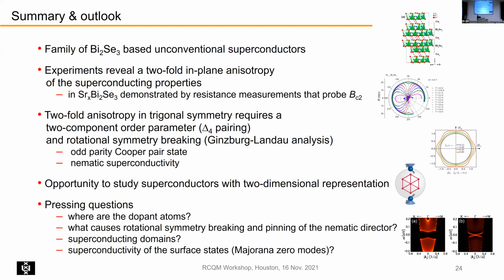Just a quick one. I remember in the context of copper doped bismuth selenide, the claim was that the superconducting volume fraction was very low, like 65% or something. Yes, maximum 60%. And when you tunnel into the surface, very little of the surface actually shows any signs that the material is superconducting. Is it better in niobium and strontium doped? Niobium, certainly there are samples, maybe because of this misfit phase contribution. There's a very nice transition also in the specific heat. For the copper doped case, there's always a larger residual gamma value. But for niobium, you can have better superconductivity.